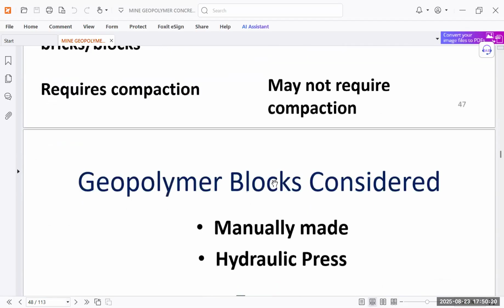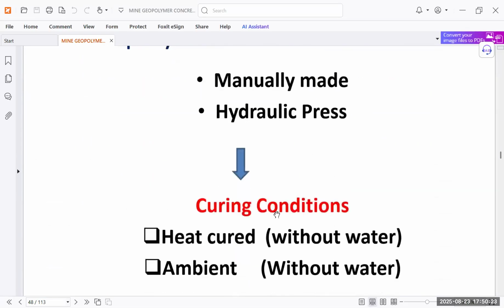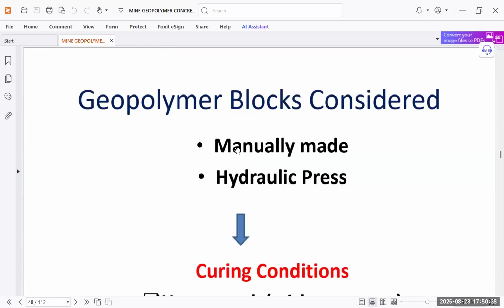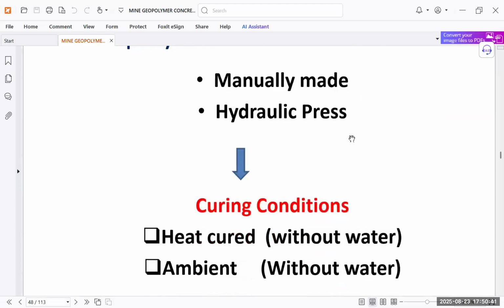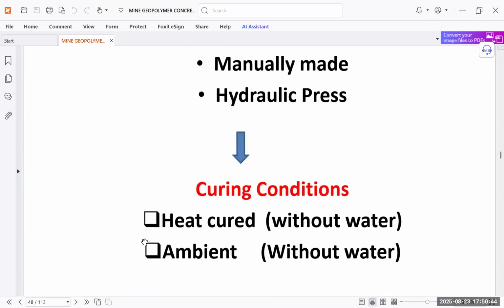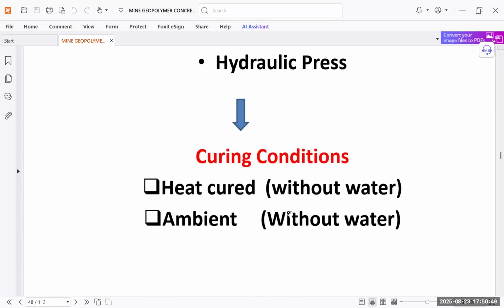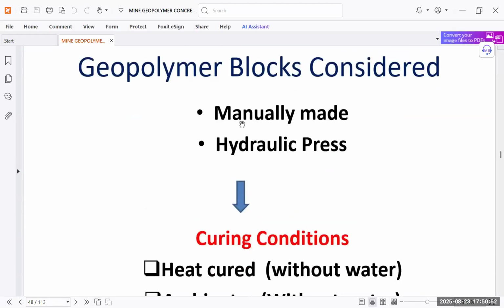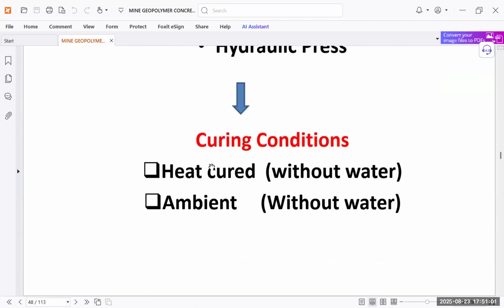So geopolymer blocks we have made manually and with a hydraulic press, and then curing conditions: here curing is done without water. That is very important. Water is not required. So you can see that heat curing and ambient curing are both done without water. So you can see that water is saved in the case of geopolymer blocks. No water is required during the curing. So that is why we are saving the water and also getting the required result as in case of concrete. That is why it's important.